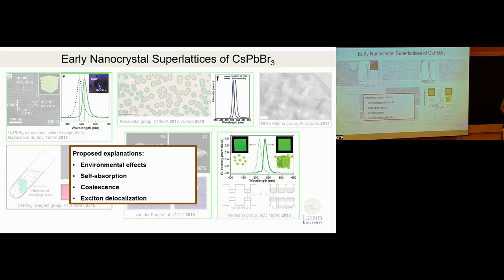Another explanation is self-absorption. Because the Stokes shift between absorption and emission is relatively small in perovskites, once you put a lot of nanocrystals close to each other, part of the emitted light will be reabsorbed and then re-emitted, and that would cause a kind of filtering effect and artificially shift photoluminescence to the longer wavelength. Another explanation was the coalescence, so nanoparticles fuse together forming bulk-like particles with a smaller band gap,